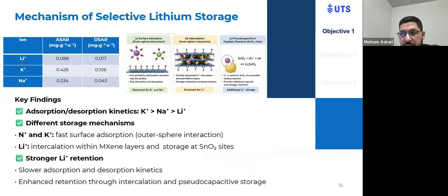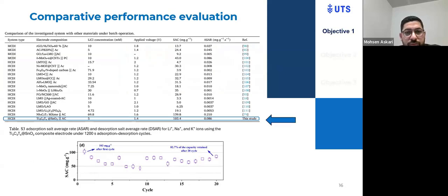As we can see in this table, the adsorption and desorption kinetics were compared for potassium, sodium, and lithium. Sodium and potassium have fast surface adsorption. They have fast adsorption and fast desorption at the same time. Whereas lithium has slower adsorption and slower desorption, and it shows the intercalation with the MXene layer and storage at the SnO2 site. So the slow adsorption and desorption kinetics of lithium help to have higher retention through the intercalation and pseudocapacitive storage of the electrode.